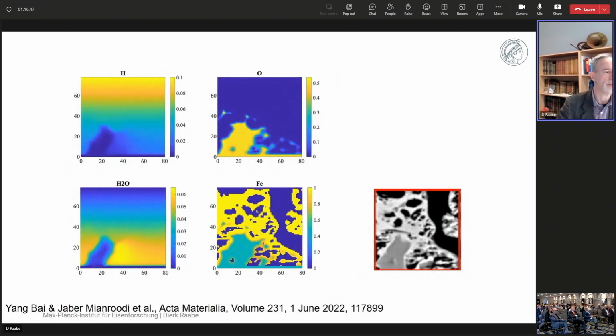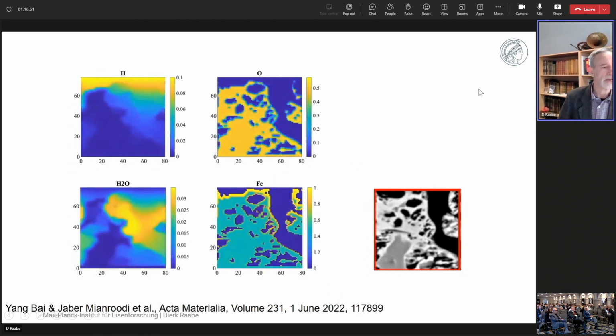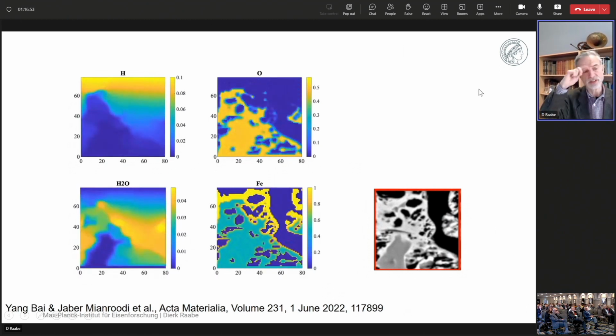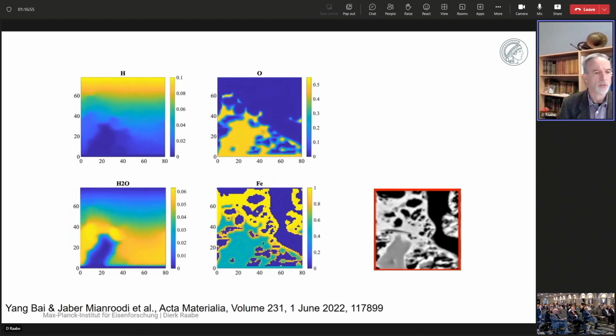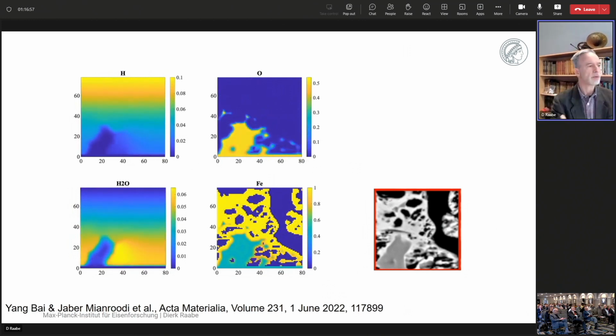Here you can see how the iron is growing. Let me run this once again. And this is fully mechanically coupled, so you can see the full details in the Acta paper. So we started off just by having a very simple elastic approximation where you reduce the lattice parameter by removing the oxygen gradually from the corresponding lattice, translating this into a Hooke strain. This adds to the elastic potential of the Landau functional.